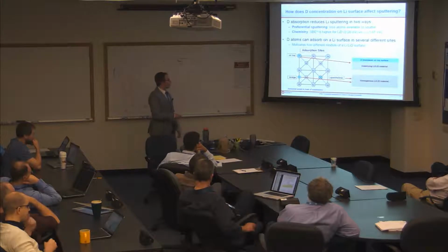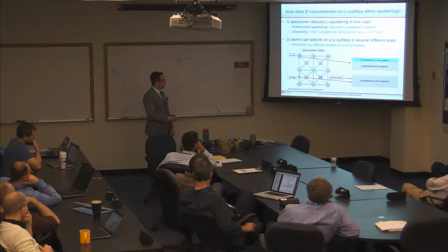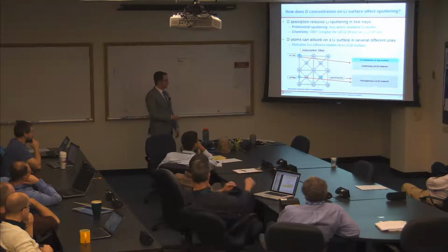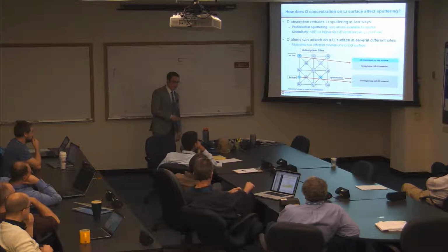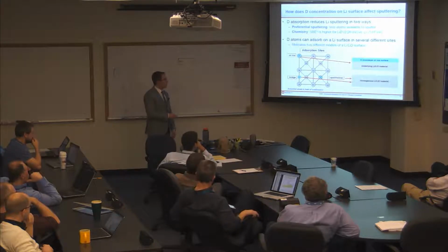And so you imagine that if they're on top, you have a deuterium monolayer forming on top of your top surface. But if they're adsorbing deeper into the material, deeper into the first unit cell, then you have more of a homogeneous lithium deuteride material right near the surface. So whether you simulate this or this will actually give you different predictions for what the preferential sputtering rate should be. So it's something to keep in mind when establishing error bands on our prediction.